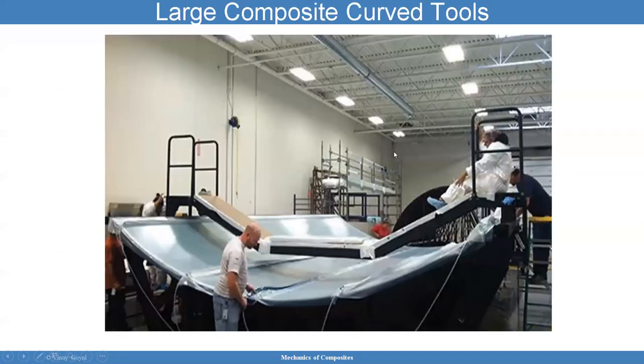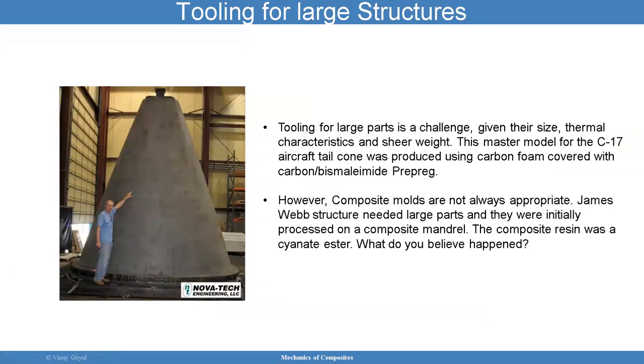And here you have large composite curved tools. That's a single person, you can see how big it is. So here you have tooling for large structures. This is very challenging. Tooling for large parts is a challenge. Given their size, thermal characteristics, and sheer weight, this master model for the C-17 aircraft tail cone was produced using carbon foam covered with carbon bismaleimide prepreg. So something to keep in mind, not very easy, but required.